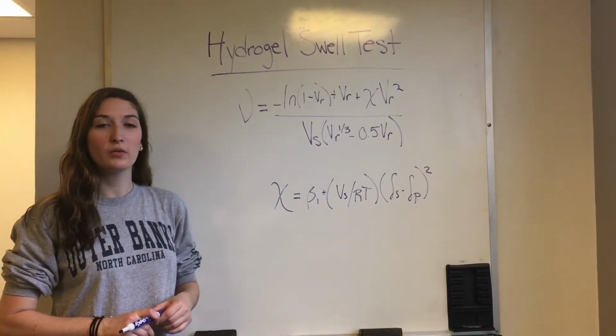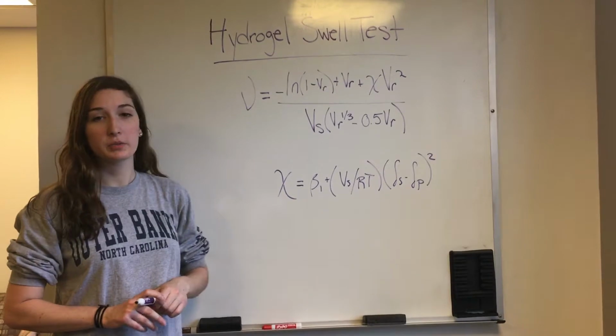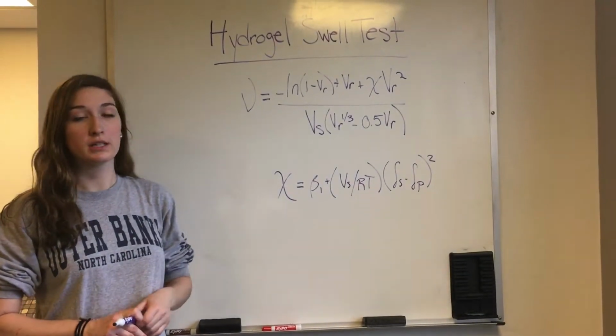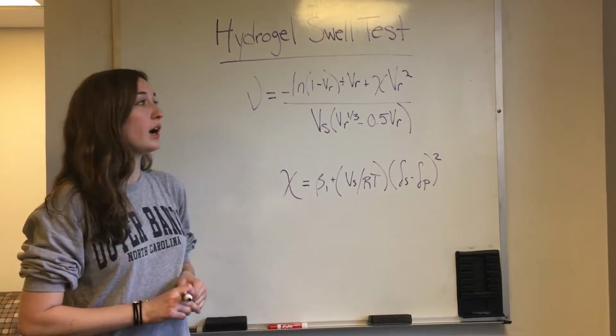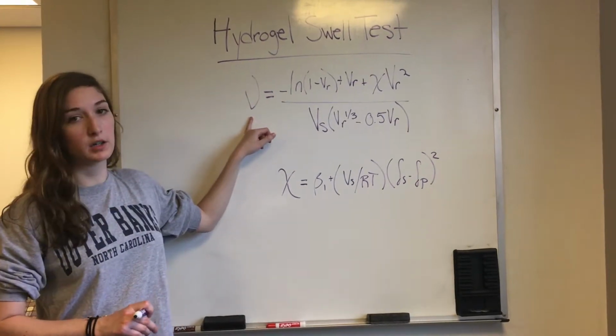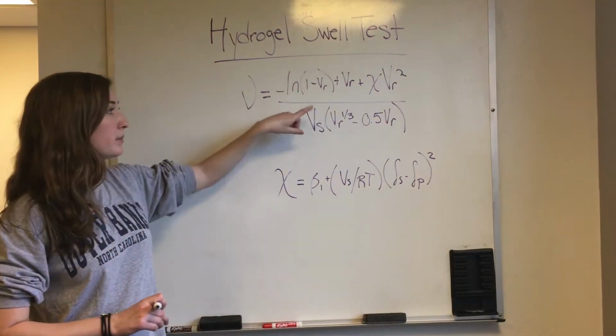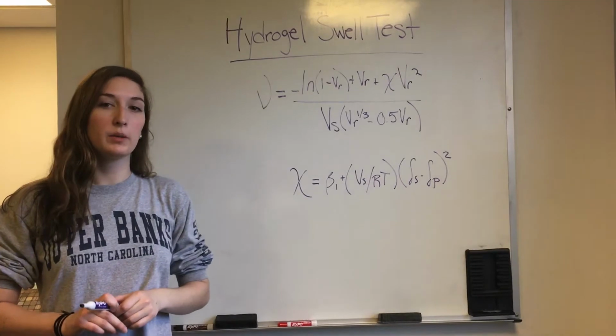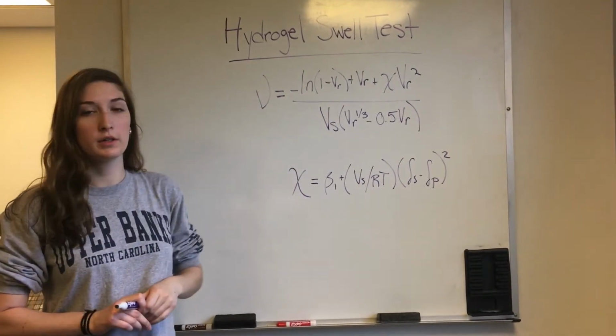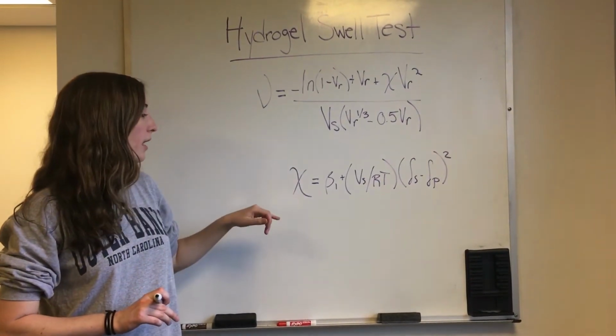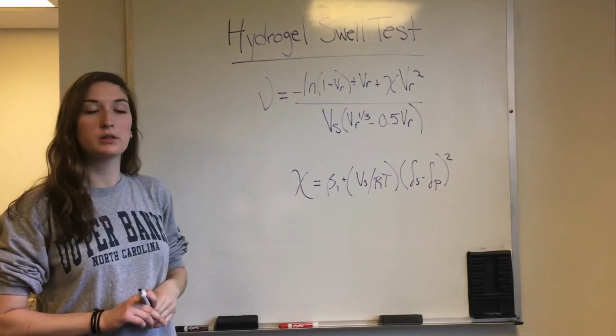So I'm going to go over how we did our hydrogel swell test, and that was in order to determine the cross-linking density of our polymer matrix. Using this equation, we were able to figure out the cross-linking density, where V sub R is the volume fraction of the polymer in the swollen gel, and V sub S is the molar volume of the solvent. And then chi is figured out from the Bristow-Watson equation here.